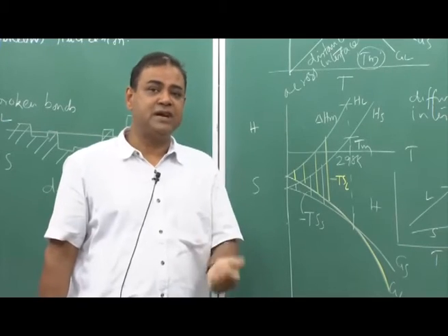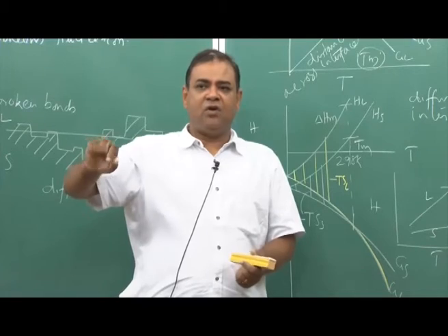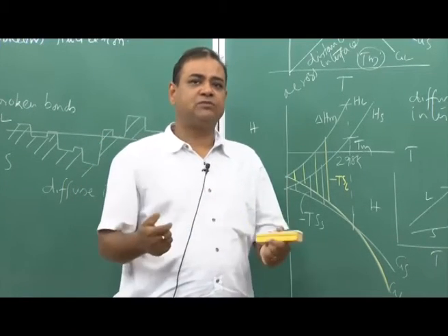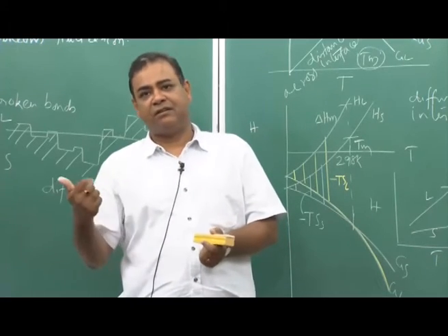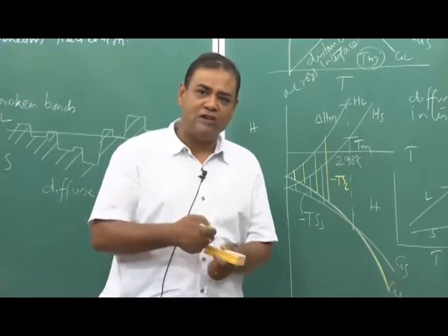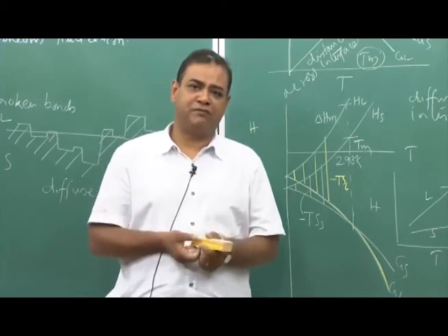The negative contribution comes either from getting rid of the interface or adding a volume free energy term. That would decrease the free energy, but interface creation would always increase the free energy. So, that is not a requirement for nucleus formation.